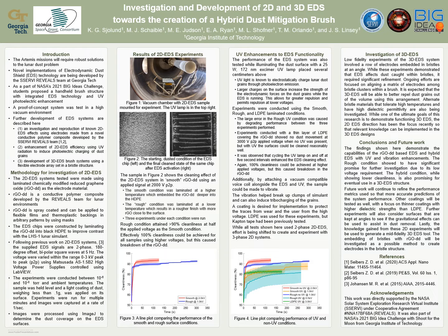Figure 3 shows the mean cleanliness achieved from the two conditions using only EDS. Both were able to achieve greater than 90% cleanliness, but the rough condition was able to do so at 1000 volts peak to peak, while the smooth condition required 2000 volts. Higher voltages could achieve near complete cleanliness, but doing so causes breakdown of the RGO.